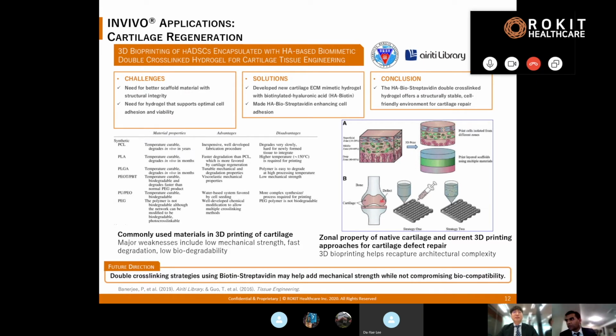with the appropriate growth factors as well as mechanical strength and a right decomposition rate for the biomaterial that they incorporated. So they actually introduced a photoreactive ink incorporating hyaluronic acid and biotin and streptavidin. So this double cross-linking gel offered a very structurally stable and cell-friendly environment for the cartilage repair. And here you will see some of the existing materials or common materials used in printing of cartilage. They come with a set of pros and cons, but none of these are perfect.